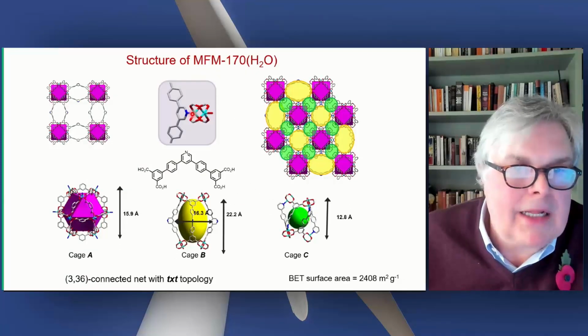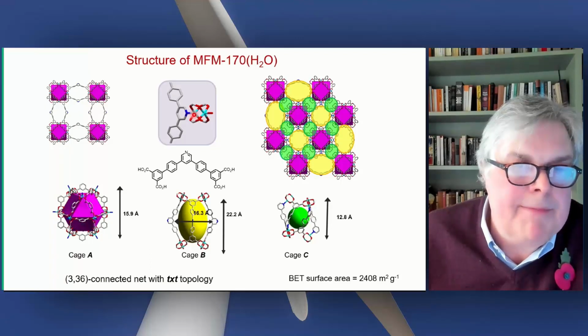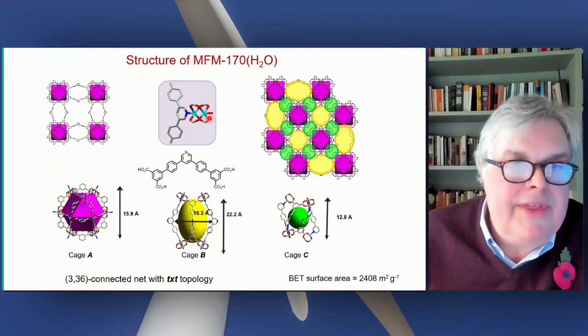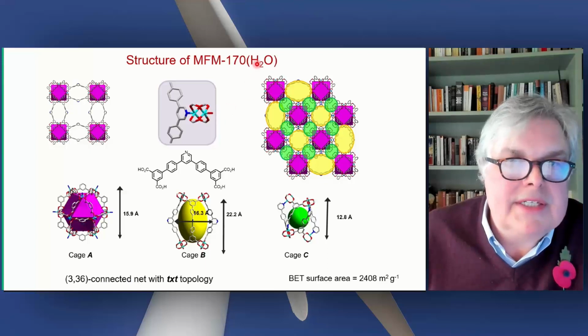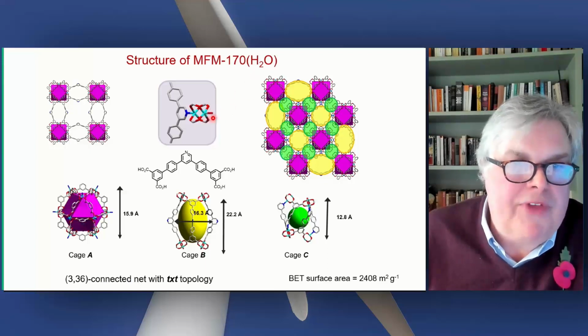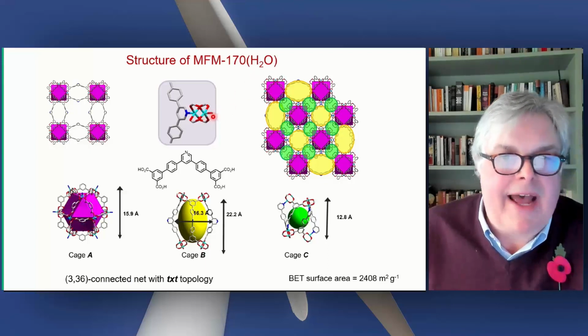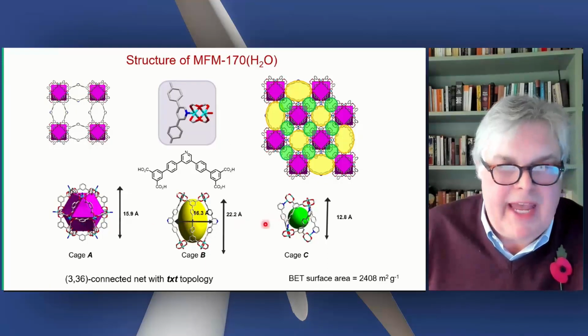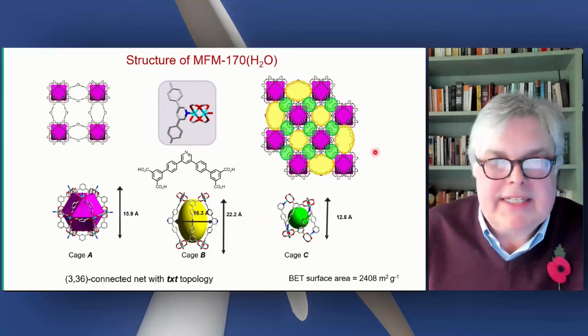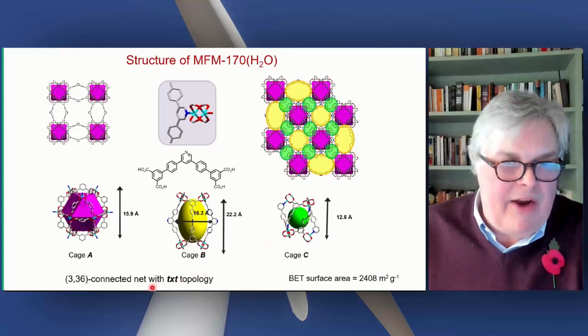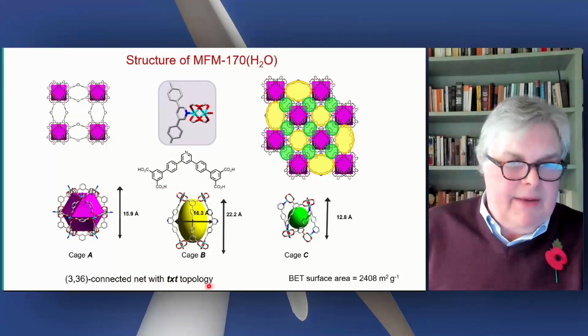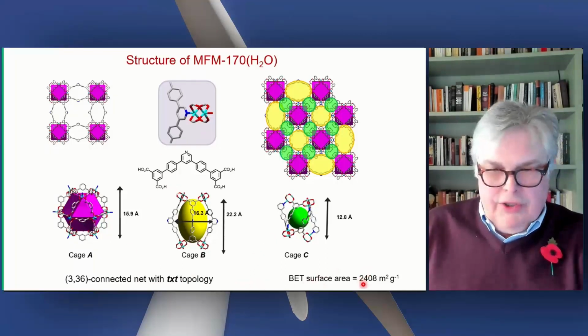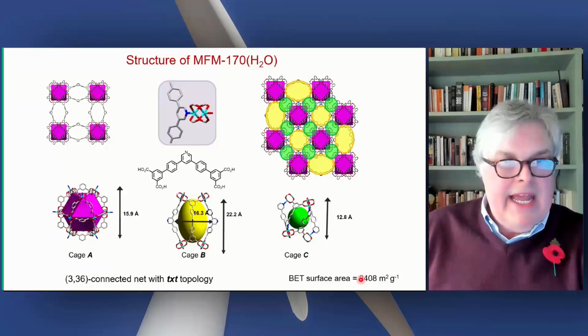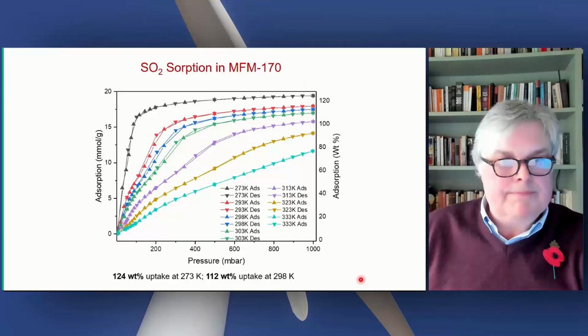Here is the copper paddle wheel. There is the nitrogen from this ligand coordinating to the copper. So that site is completely blocked. This copper has a water. This is this water, and you can remove that water by heating under vacuum. You've seen these types of cages before. This is how they pack. There are various very interesting structural perspectives here, which I won't go into. It has a good surface area, and as I say, is very stable.